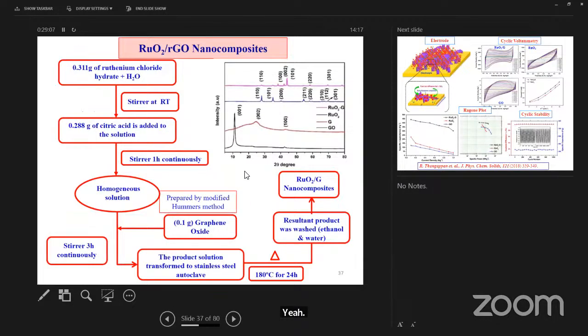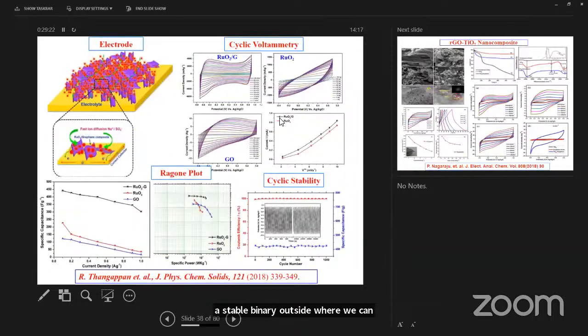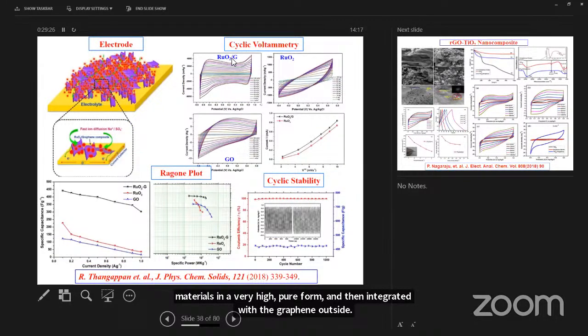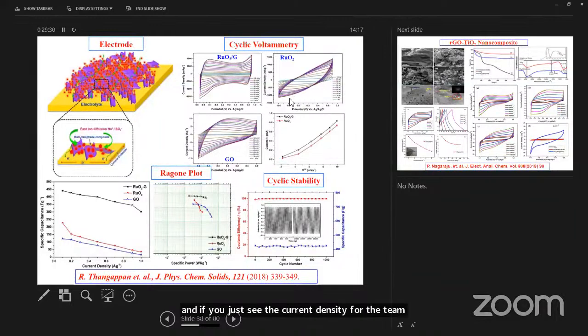So this is actually the RGO, ruthenium oxide RGO composite. As I told, ruthenium oxide is a stable binary oxide where we can prepare these materials in a very high pure form and then integrate with the graphene oxide. And if you just see the current density for the ruthenium oxide graphene composite, it is also reasonably good, and the energy density and power density were measured for this.